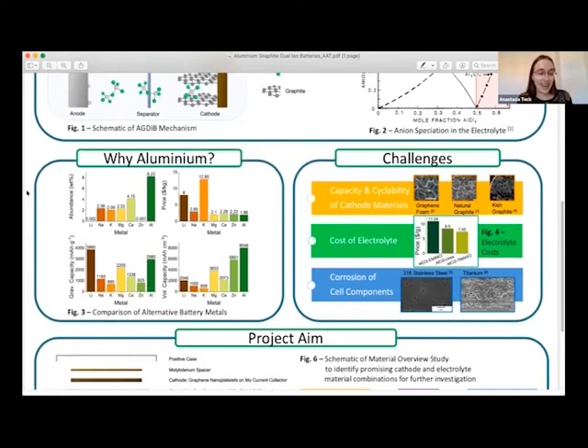Second, the high cost of the traditionally used EMIC chloroaluminate electrolyte has motivated research into the use of deep eutectic solvents like urea chloroaluminate or alternative ionic liquids such as trimethylamine hydrochloride chloroaluminate, which are cheaper at comparable performance. So research into different electrolytes may further reduce this cost.